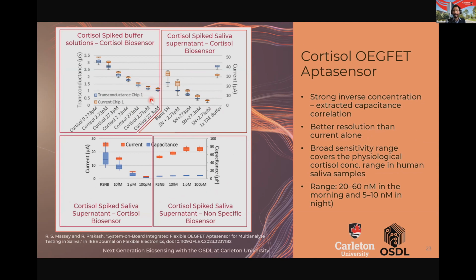And this correlation can be used to extract other meta parameters, for example, extracted capacitance, which is the system's way of doing a sanity check that the data that we are collecting is real data. So we collect other parameters which corroborate that. The range is excellent. You can see that it's sensitive and specific, so it doesn't interact with non-specific analytes. And for cortisol, we tested in synthetic samples and in saliva samples to establish the detection range and compare it to the physiological range of cortisol in saliva samples.